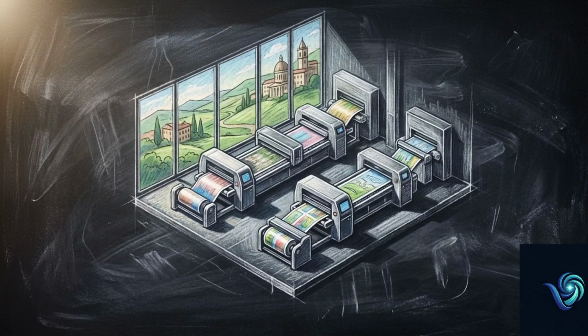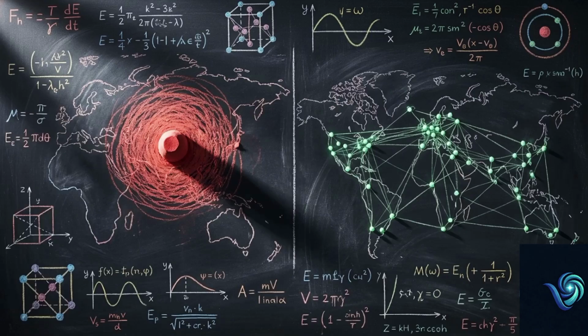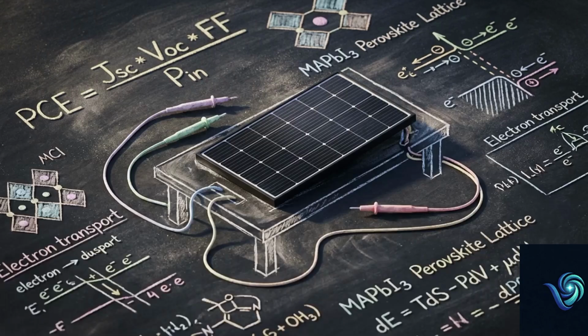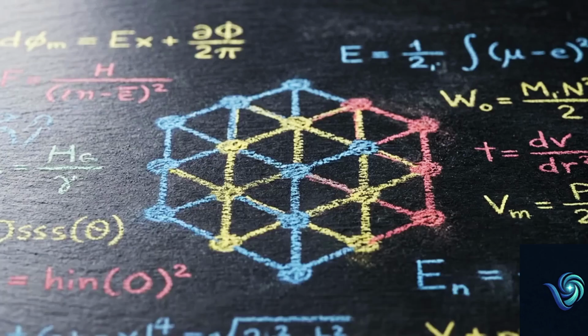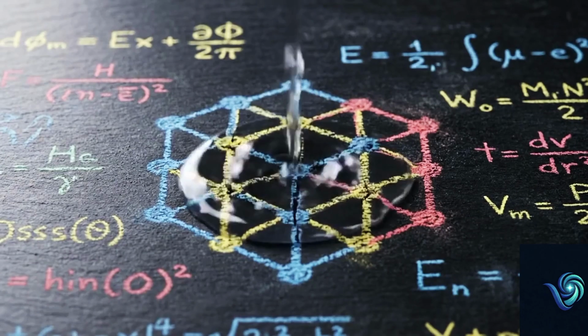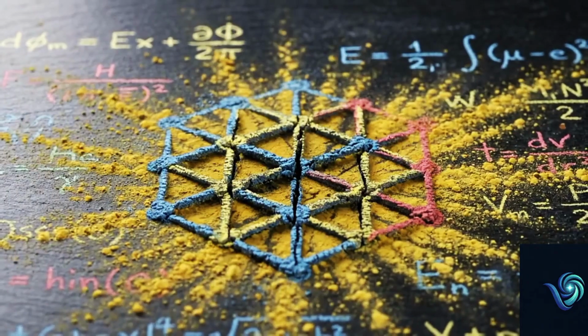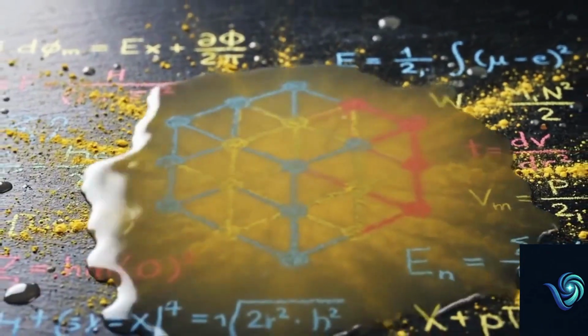Because perovskite final stage printing requires low capital expenditure, this decentralized manufacturing becomes economically viable far outside of Asia. This regional manufacturing model relies on the low capex nature of perovskite to function, providing an alternative to the geographic concentration of traditional silicon. Despite the low costs and laboratory records, perovskite solar cells remain largely absent from the commercial market. The primary physical vulnerability is the organic component of the lattice. Because it is highly water-soluble, the material degrades rapidly upon contact with moisture.